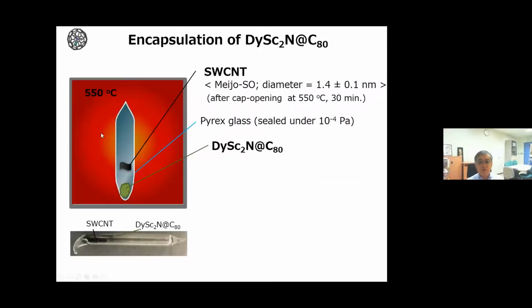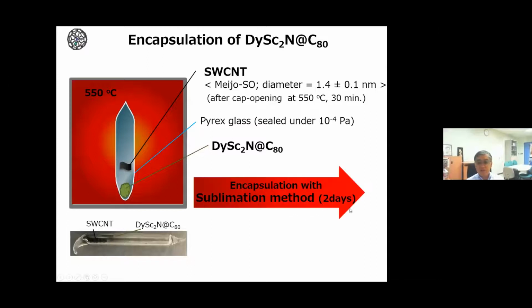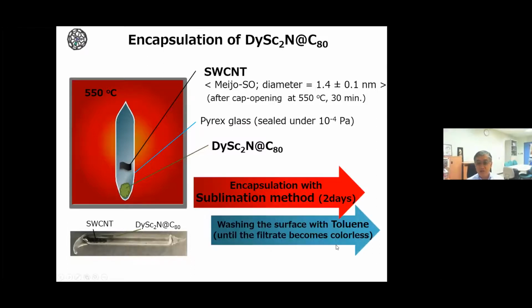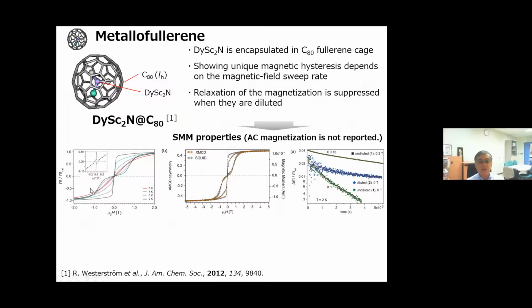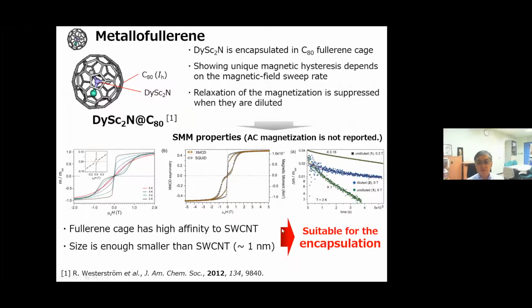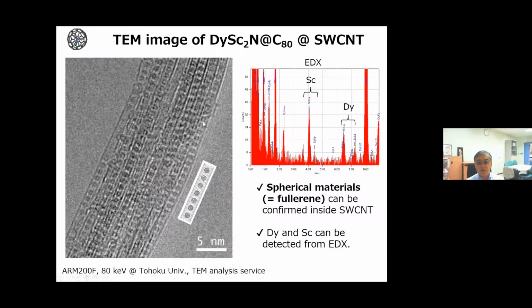So high vacuum condition and high temperature, a few days, and wash outside. So this starting material, as you observe, is actually a single molecule magnet. So we encapsulate this into the single wall carbon nanotube. So this is a result, TEM image. So you can see spots are observed. This is the encapsulated metal fullerene single molecule magnet, like this.